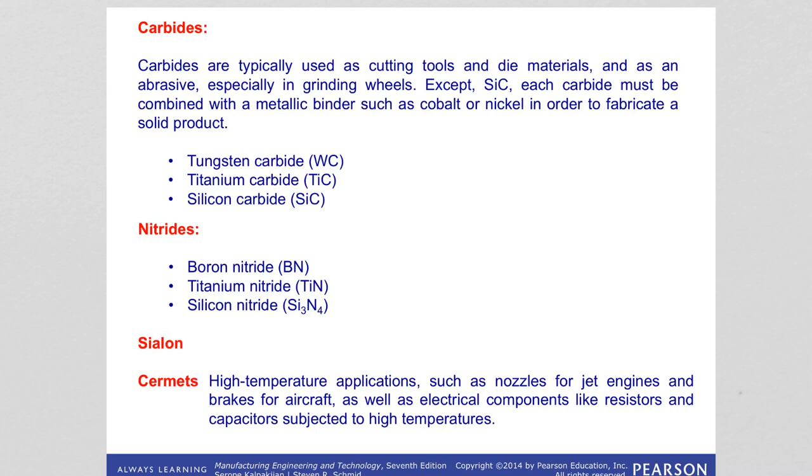It actually oxidizes at about 1200 degrees C. It chemically decomposes at around 1900 degrees C. Therefore, it is used in components like automotive engines, gas turbines, rocket engines, melt crucibles, bearings, nozzles, etc. So high temperature applications.